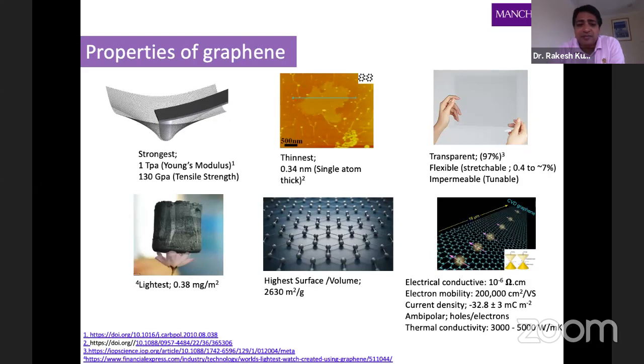It's the lightest and the strongest, but at the same time, it has a high surface to volume ratio because every single atom is basically a surface atom. There's no bulk material. And because of all these properties, graphene is a superlative in terms of electrical conductivity. You get a mobility of charge carriers around 200,000, compared to any other material. Graphene is called ambipolar because, as we said, there's no band gap and you can switch the charge current from electrons to holes by modifying graphene with a gate voltage.